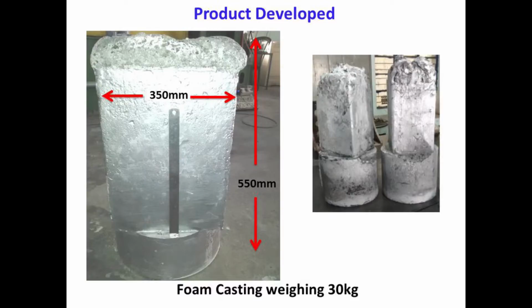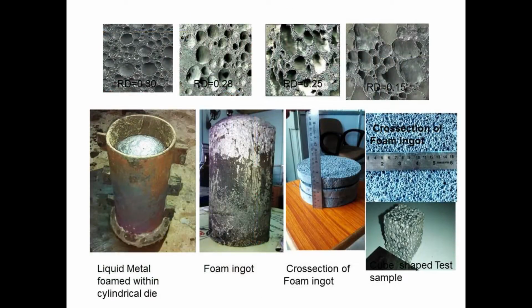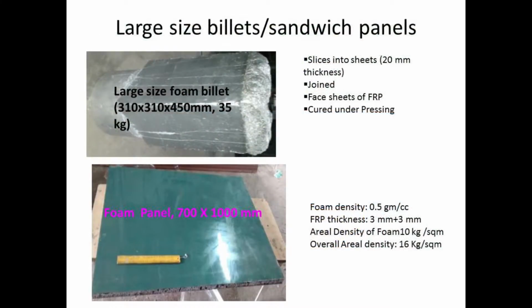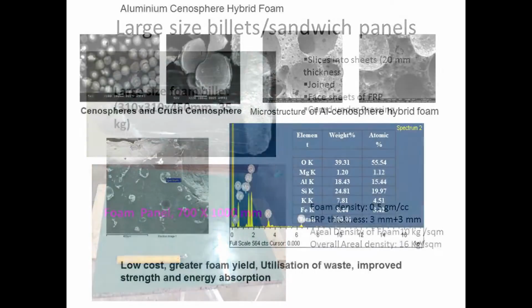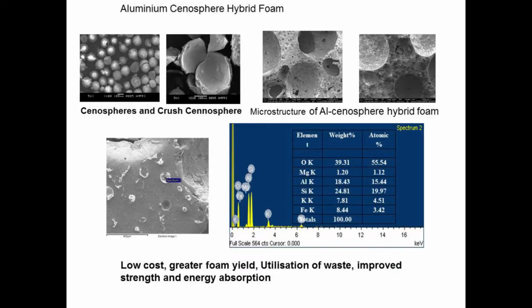And if we see the microstructure, depending on the foaming temperature, we have different sizes of the pores. And if the pore size increases, we will get different density. We have achieved a density up to 0.25 gram per cc, because this material is needed for crashworthiness. It should have very low density. But for structural application, like sandwich panels and other things, it needs higher strength. So there we can also make a foam having a density of 0.8 to 0.9 gram per cc.